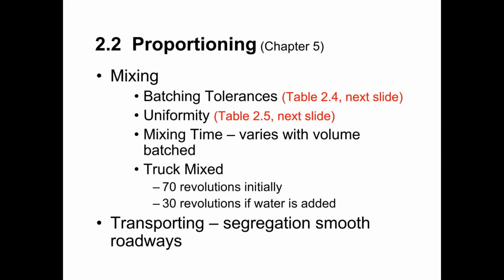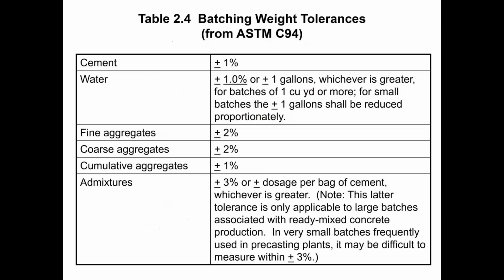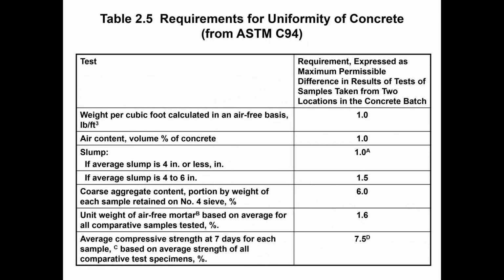All right, uniformity is another requirement, table 2.5. This comes from ASTM C94, which is the ASTM standard with regard to ready-mix concrete. So these requirements for uniformity are generally applied to truck mixed concrete. All right, centrally mixed concrete, generally we don't have these uniformity requirements. You could still use this uniformity parameter to do a uniformity test on centrally mixed concrete, but generally centrally mixed concrete is going to meet these requirements. It's truck mixed concrete that this is primarily intended.